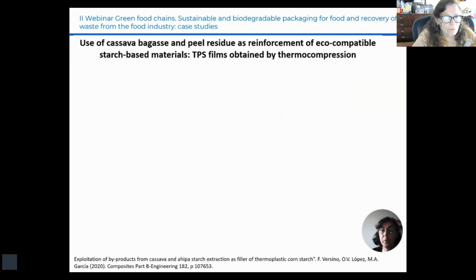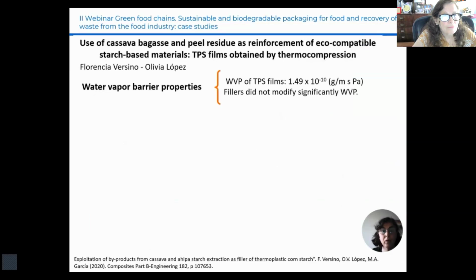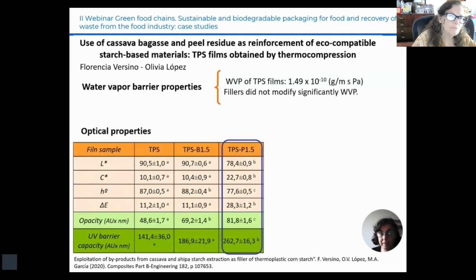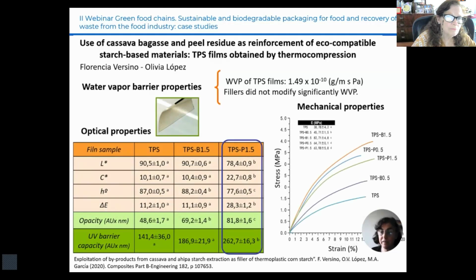Both bagasse and peel residue were used as reinforcement for starch-based films obtained by thermocompression. This work was carried out in collaboration with Dr. Olivia Lopez. While the reinforcement did not modify significantly the water vapor permeability of the materials, a clear effect was observed on the mechanical properties, where both acted as a reinforcement, increasing both the elastic modulus and the material strength. Furthermore, while the byproducts, particularly the peel residue, impart color to the material, as you can see in the photograph, they also improve the UV barrier capacity, which is a very interesting property for its use in agronomic application, such as soil mulching.